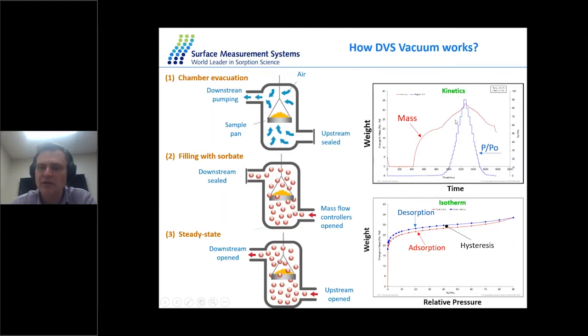As you can see from the steps here, after the initial steps, the subsequent steps in partial pressure of water and the mass equilibrium are relatively fast. When I step up the partial pressure from 0 to 90%, it is called adsorption. When I step down the partial pressure of water from 90 to 0%, it is called desorption. In this process, I am removing the water molecules from the sample, and as a result the sample is losing mass.